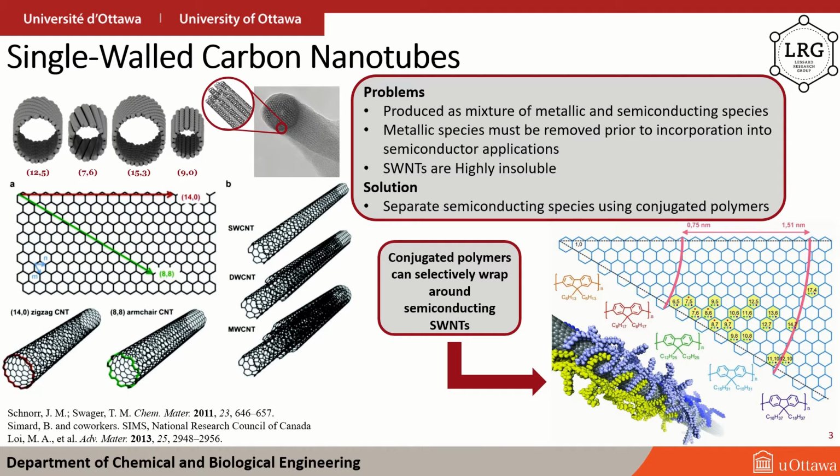Single-walled carbon nanotubes are an allotropic form of carbon, analogous to a sheet of graphene rolled into a tube 1 to 2 nanometers in diameter. The high degree of conjugation and the one-dimensional density of states gives carbon nanotubes an exceptionally high electrical conductivity, alongside mechanical flexibility and thermal stability, making them ideal candidates for incorporation into flexible electronics to help improve device performance.